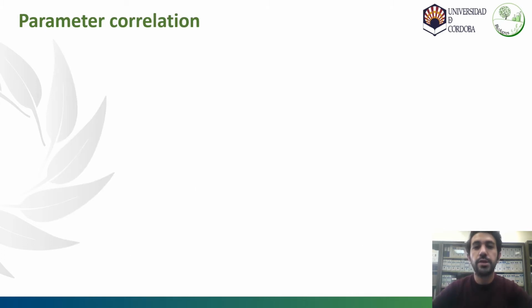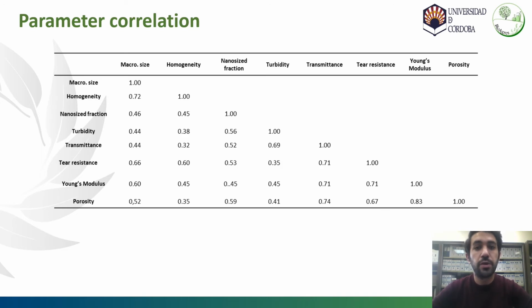In the end, the objective that we search is an easy and fast quality index that allows us to evaluate all the properties of the nanocellulose. Then, it was proposed to limit the number of criteria required for the calculation of this index by means of a correlation matrix between the different parameters. Beyond a correlation value of 0.6, it was considered that both parameters are dependent, and that this dependence is high when it exceeds the 0.7 value.